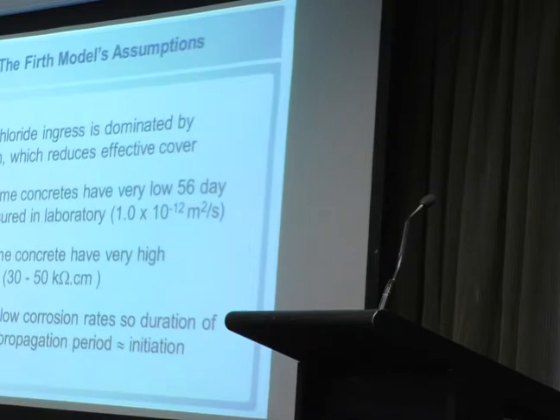It was more of an attempt to take account of the realities of the situation. So, for example, it said that the initial uptake of chloride ions in most structures is going to be by capillary absorption. That's going to be quick and is effectively going to reduce some of your cover. It considered diffusion coefficients measured on laboratory specimens.